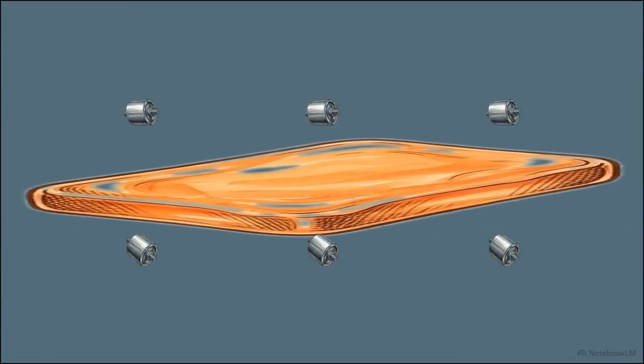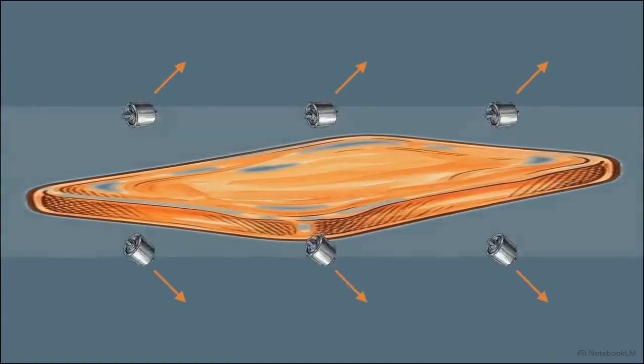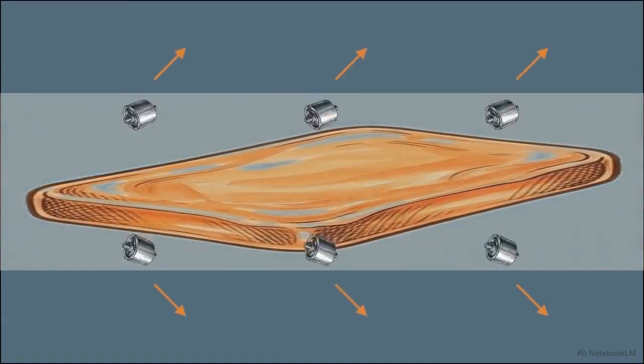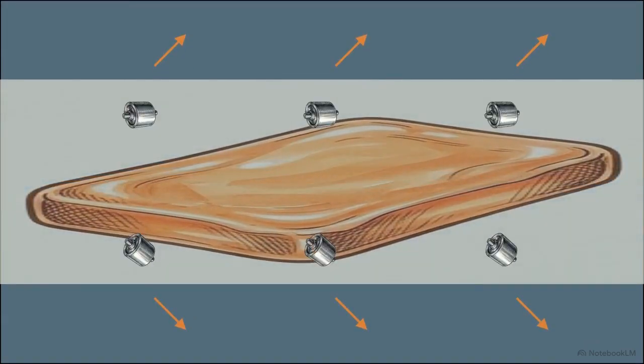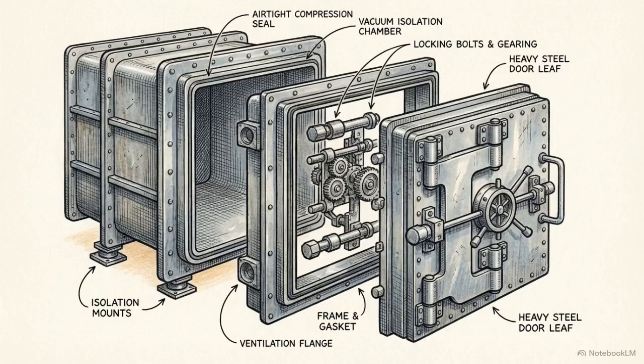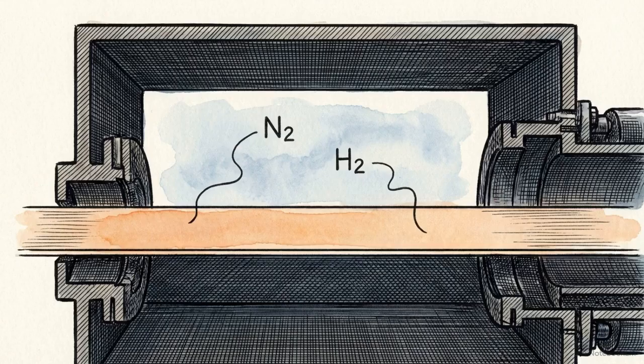To control the exact final thickness, mechanical top rollers grip the edges of the semi-molten layer. By speeding up the rollers, the machinery gently stretches the outward spread of the glass to make it thinner. To keep the liquid tin from oxidizing and ruining the process, the entire bath is sealed within a carefully controlled atmosphere of nitrogen and hydrogen gases.